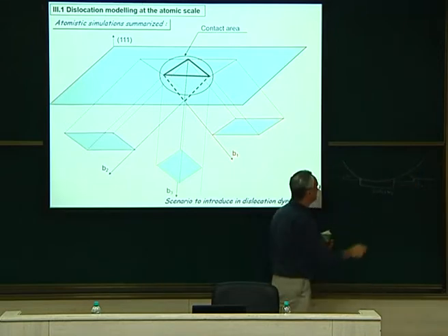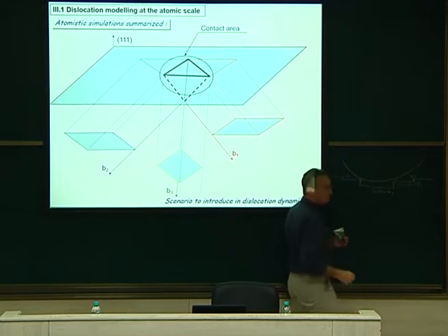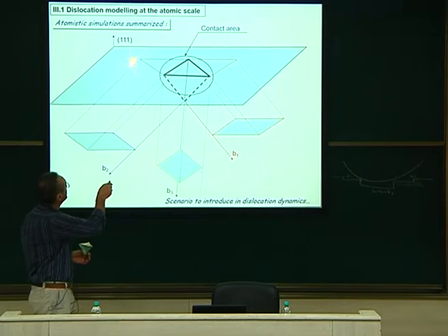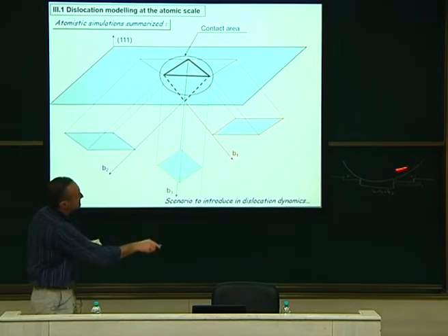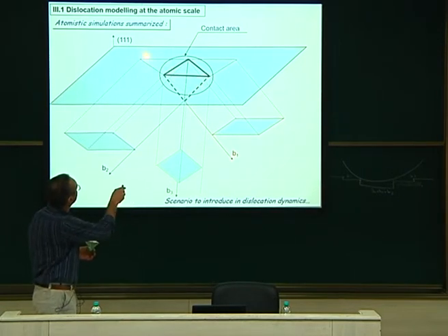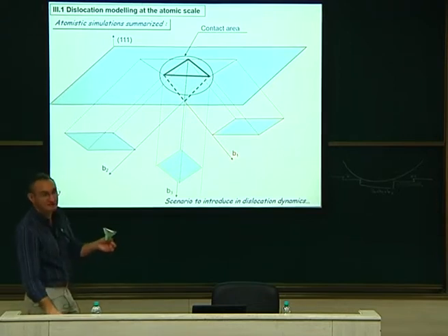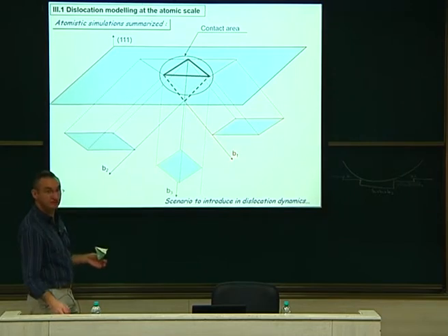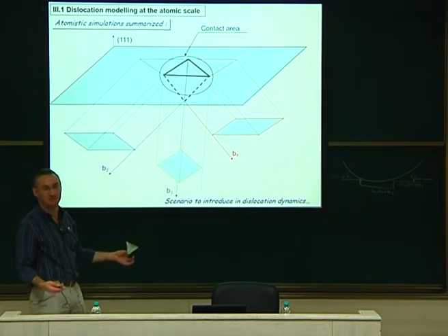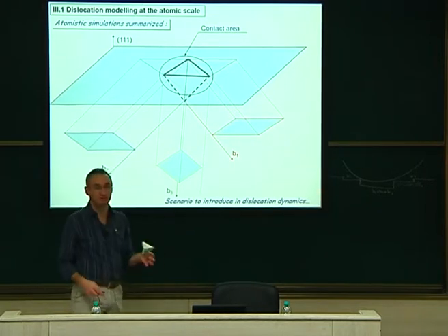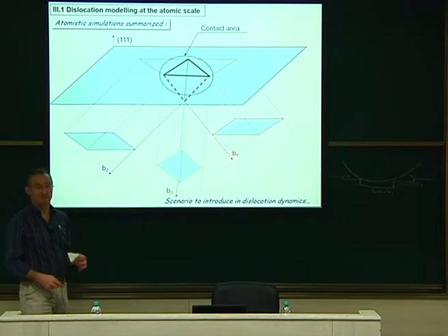You see what I want to plot here? So this is the deformation if I was cutting a plane here through that zone, for example, like that. Well, it's wrong because I cannot go through the two, but if I go that way and that way, I have B1 plus B2 plus B3, and this B2. Like this, okay? So you have some stairs which accommodate, roughly, the contact with a sphere. It's not a sphere, of course. You cannot create a sphere with a single dislocation, but you have something like that which accommodates the spherical contact as best it could. You see, so that's normal.